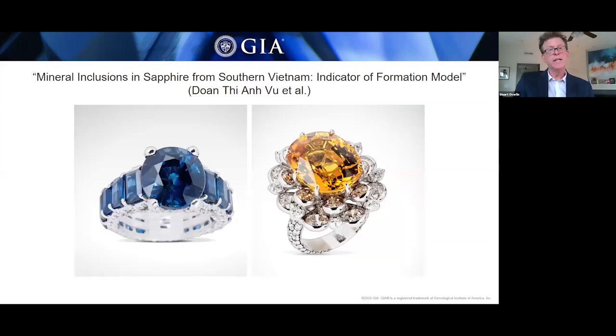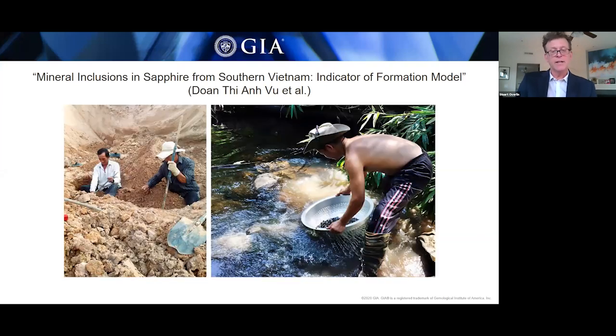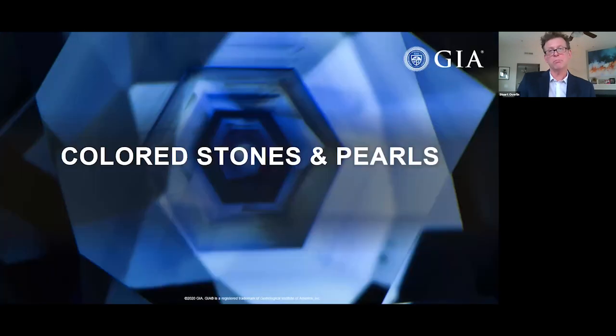And finally, Duan Vu, Shakapan Sudarat, and co-authors investigate mineral inclusions in basaltic sapphire from southern Vietnam, which you see in these 2 rings. The authors analyzed the chemistry of these inclusions to better understand the formation model of the sapphires in relation to the basaltic volcanism of the locality. And without any further ado, we'll get started on colored stones and pearls, brought to you by Nicole Aline. Here's Nicole.